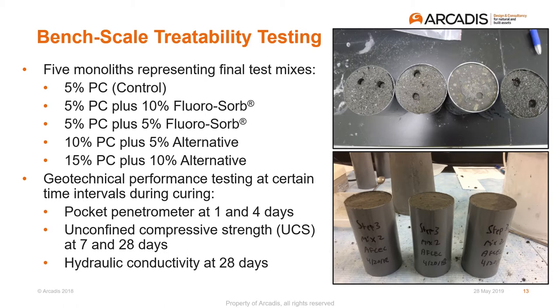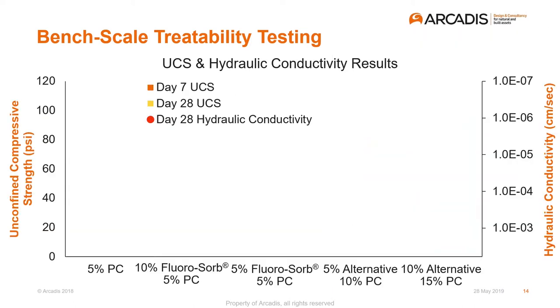The geotechnical testing that was performed was pocket penetrometer at 1 and 4 days, which is basically a handheld push pin that you push in just to understand that you're getting some sort of compressive strength. But then we also did unconfined compressive strength tests at 7 and 28 days and looked at hydraulic conductivity at 28 days. So for the data, just setting up this plot, on the far axis we have unconfined compressive strength in pounds per square inch. On the near graph, we have hydraulic conductivity, with higher hydraulic conductivity at the bottom and lower hydraulic conductivity at the top, just to try and confuse you, and then all the different formulations that we tested.